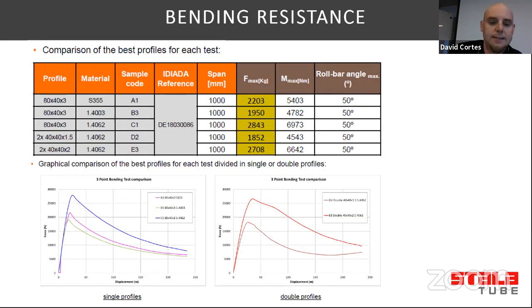So the reason for that is that the side wall in the middle of the tubes prevents local buckling. And just by using two tubes side by side, this 40x40x1.5 has almost the same maximum bending moment as one single 80x40x3 carbon steel tube. So there is a potential weight saving.